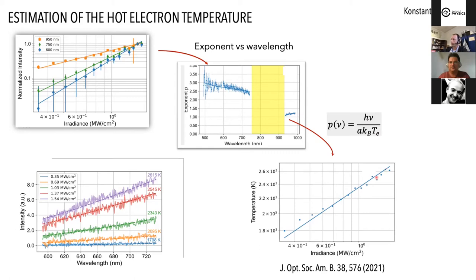And this is, in a very good approximation, the one that has been simply deduced by fitting the curve with Planck's law. So we have a nice one-to-one correspondence between these analyses. Of course, the underlying physics is the same; it's Planck's law, but we have two ways of bringing Planck's law into the system. So everything seems to be consistent with this hot electron picture.